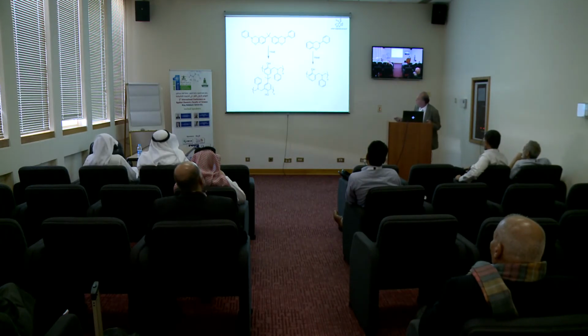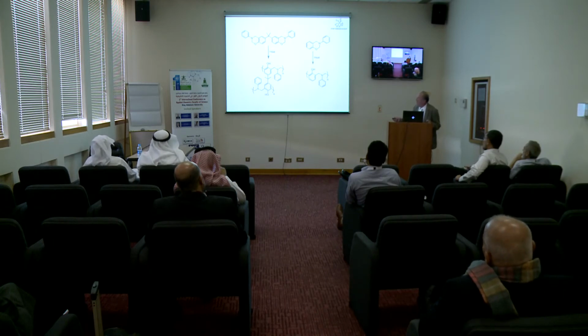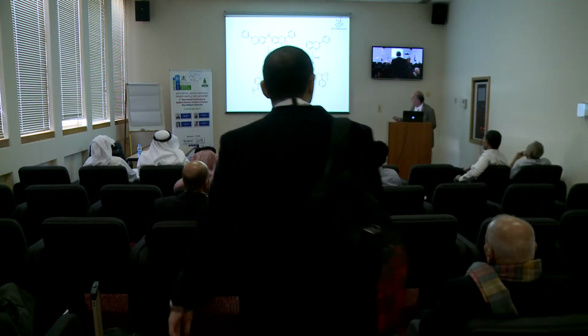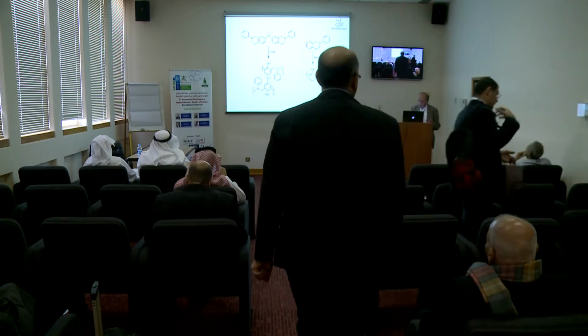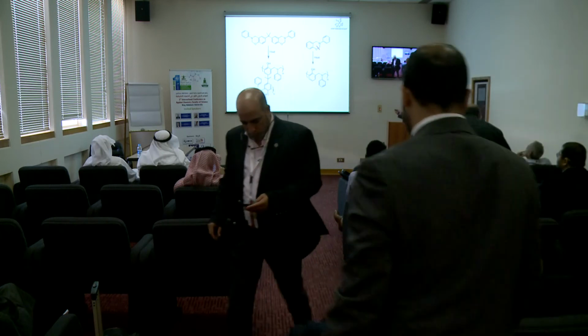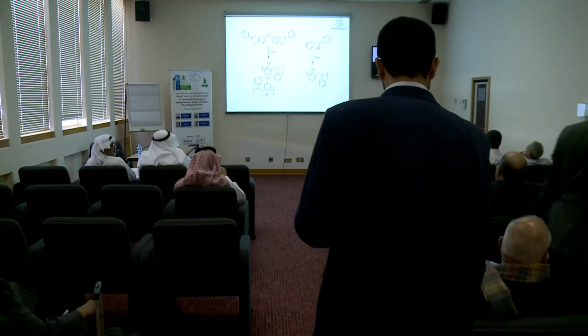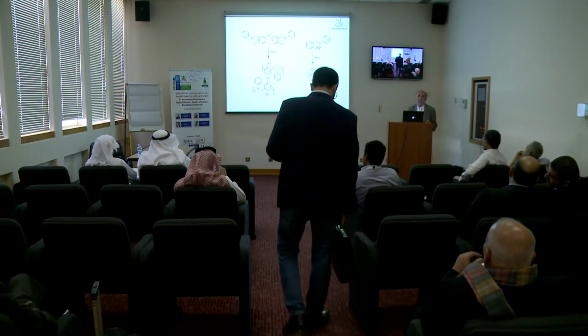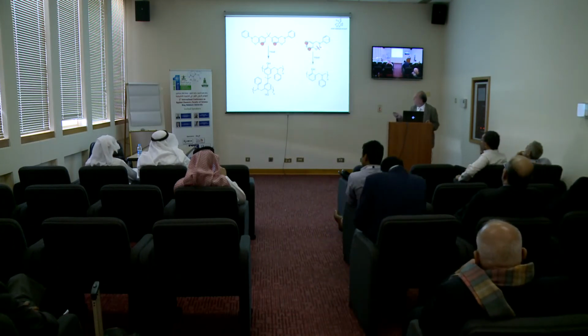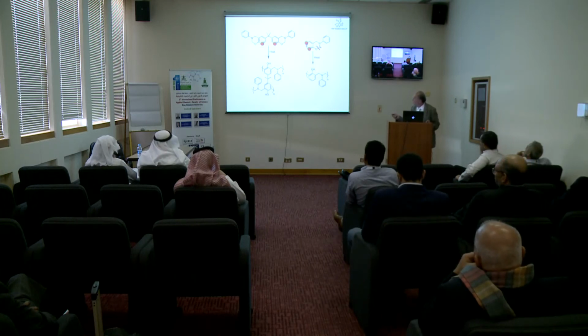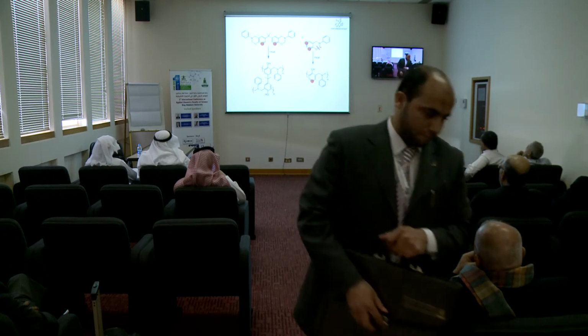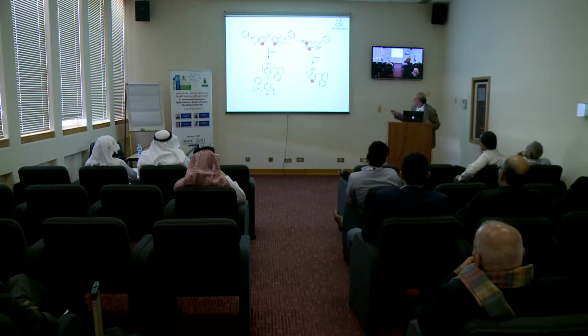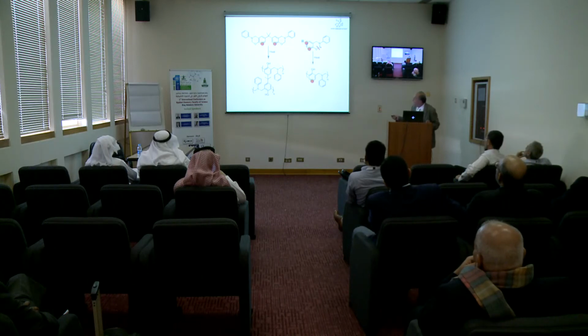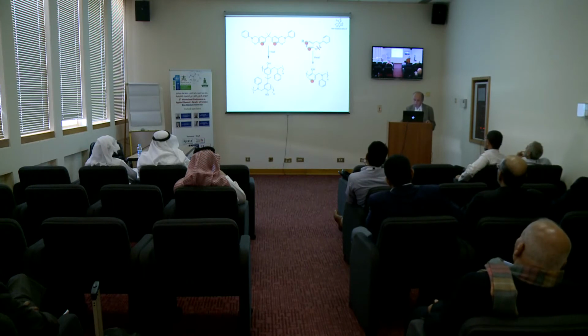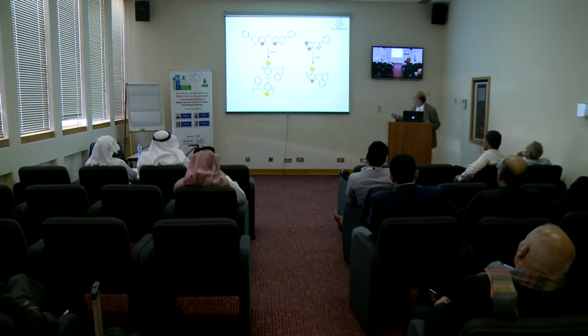So the chemistry is, as I told you, if you heat it you have a polyphenol like bakelite, phenol-formaldehyde resins. You can prepare them even from monofunctional ones, because by heat there is a bond breakage, and this bond breakage causes the formation of a cation, which may attack these positions, or in a bifunctional one here, and you end up with cross-linked ones. These are useful, as shown here, maybe the polymer or any functional group here. So you see that you can further use them if you have such phenolic groups.